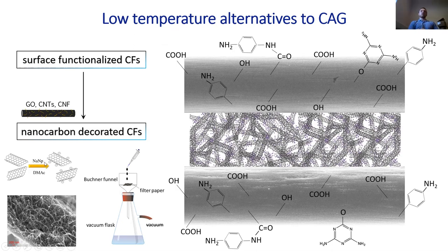So this basically involves wrapping of carbon nanotubes with a charge, which electrostatically separates carbon nanotubes, forming high surface area materials with a high concentration in the dispersion, which can be easily drop casted or infiltrated on top of the carbon fibers, forming either a vacuum infiltrated layer of CNT on the surface of carbon fibers, or ideally forming an interconnected 3D network of CNTs between carbon fiber spaces.